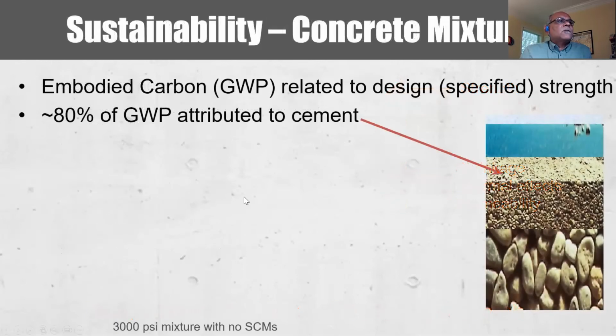Other things that achieve higher performance are improved quality control. We have to address specific durability issues and constructability. Sometimes constructability governs, where we have to use a higher cementitious content just because the concrete is being pumped, or it might be post-tensioned, or it could be that you're using self-consolidating concrete. Those tend to increase the cementitious content in the mixture. However, the specification should not restrict these goals for achieving high performance concrete.